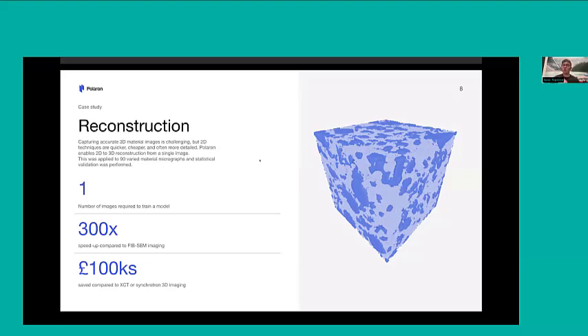So what we developed was a 2D to 3D reconstruction technique that takes a single 2D image of a material, a cross-section, and we're able to reconstruct from that single image what it would look like in 3D. Now, this happens very quickly, and comparing it to doing a 3D imaging technique, it's hundreds of times faster and saves a lot more money because we just take a low-cost 2D image and we can now reconstruct any size volume 3D that we want. And this is all done through a data-driven approach. There's no physics-based modeling here. We're not imposing any kind of statistics on it or trying to fit shapes to it. It's purely learning from the data that it sees in the image.